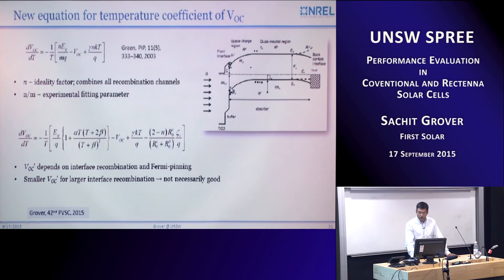And here I draw, sorry for throwing this off, but this is a P-type absorber now, more of a CdTe or CIGS-like absorber. And this term, chi I, is the distance of the minority carrier band from the Fermi level at equilibrium. So that's the strength of the band bending. That's also reflected in the built-in voltage. This is essentially, I think, band gap minus built-in voltage, something like that. But anyway, the difference here is, again, this term, which is contributed by the interface recombination, the ratio of the interface recombination over the interface plus bulk recombination. So the larger the interface recombination, the larger will be this term, and that's going to essentially